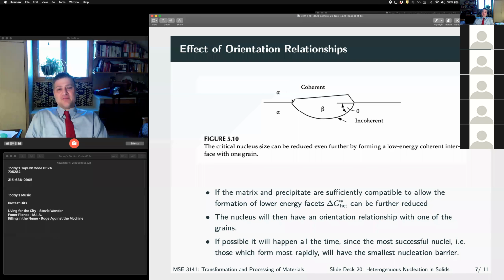Okay, but anyway, if there is a configuration that is slightly favorable energetically, that is what will happen. And that's the origin of these orientation relationships. This interface is slightly lower energy, therefore a little bit easier to nucleate. So given the statistics of nucleation, it happens all the time, right? So this is very different than our expectation of the real world, right? This is the statistics of extreme events,